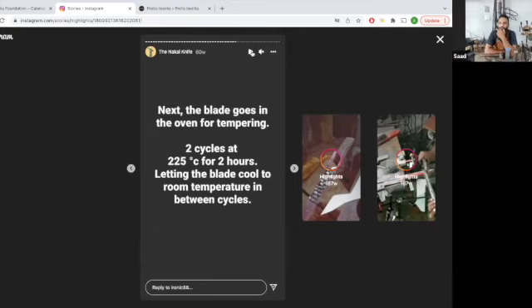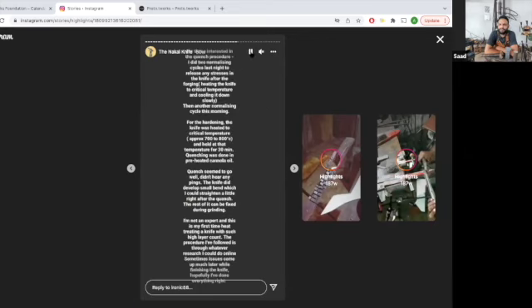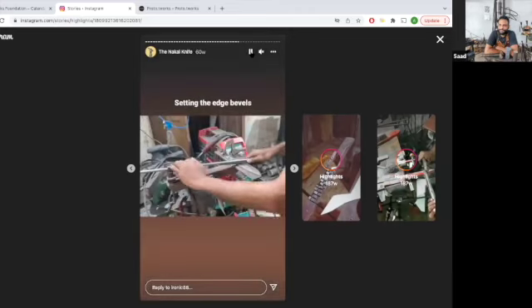Not in my forge. I use my oven, my mom's oven. So it's just 250 degrees. I do it at 240. When I first started out, I used to do it at 225, but after testing, I realized 240 works out better. So 240 degrees, 2.5 hour cycles, two cycles each. Your mom will have a cake or something baking beside your knife. But I think a cake needs about 180 degrees to bake. So if it's burnt, then I'm not responsible.